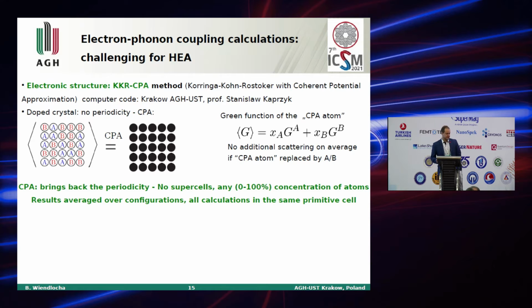So a few words about our techniques. Electronic structure in this work was calculated using the KKR-CPA method, Korringa-Kohn-Rostoker with the coherent potential approximation. We have the code developed in our institute in Krakow. And in this method, to deal with the disordered system, we use the coherent potential approximation, in which we describe the scattering of electrons from this real disordered material as an effective scattering of an ordered medium of, let's say, effective atoms. And the properties of these effective atoms are calculated self-consistently using the multiple scattering technique and the Green function technique. And thanks to this, CPA brings back the periodicity.